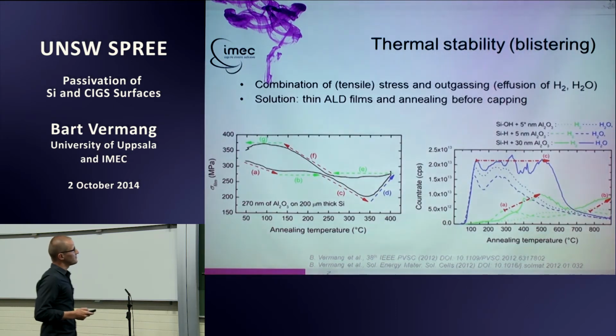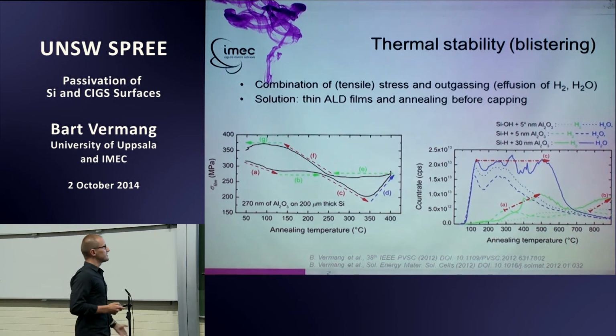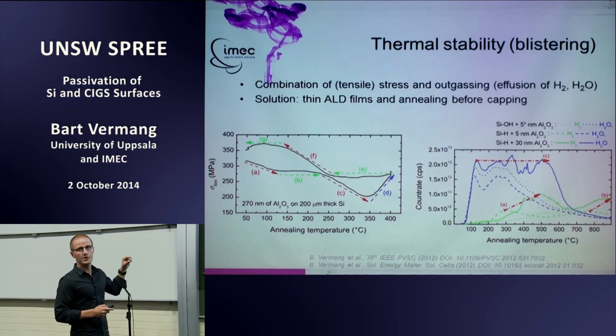What is blistering? We have been investigating this. In the end it is a combination of stress and outgassing. So the left picture you have here is stress as a function of annealing temperature for a quite thick aluminum oxide layer on top of silicon. And what you see is a cycling from 50 degrees to 400 degrees and back to 50 degrees. And in the meanwhile, you brought some tensile stress into your aluminum oxide layer. And it happens at the moment blistering starts.